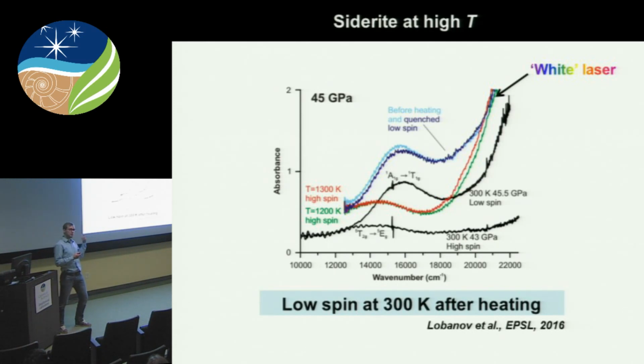The absorption spectrum of the quenched sample looks almost exactly the same as it did before we heated it. So altogether, this means that we're looking at a reversible temperature-induced low to high spin transition, and then back to low spin after we shut down the heating laser. So this is just a proof of concept that our new optical absorption system allows measuring absorption spectra at high temperature, and that these spectra can be used to say something about the spin state of the minerals we're looking at.